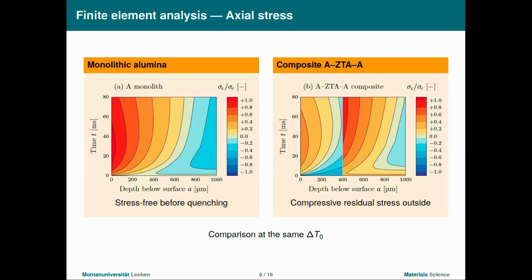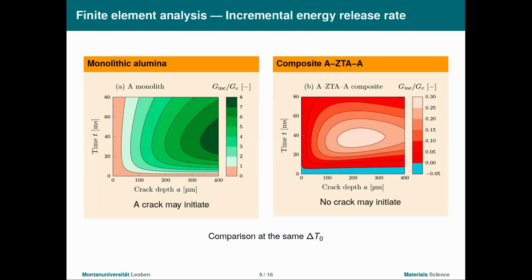Whereas in the composite, because we have compressive residual stresses on the surface, stresses on the surface are smaller, but at the same time, we are putting the core under tension. So you need to be careful and balance it out and try different designs.